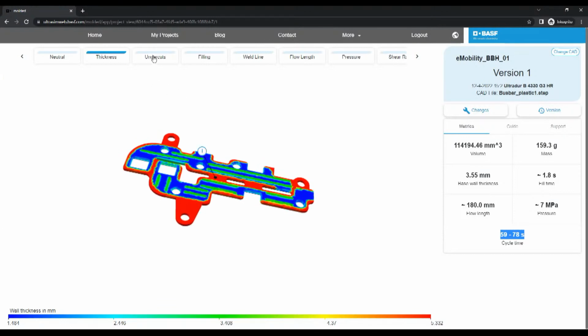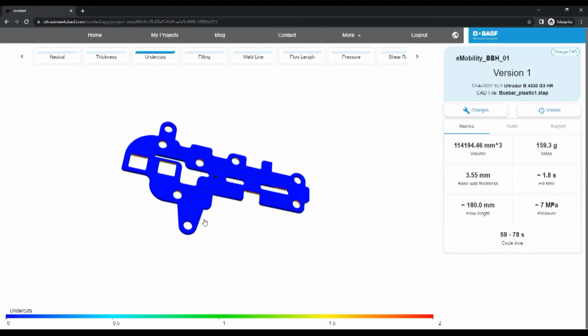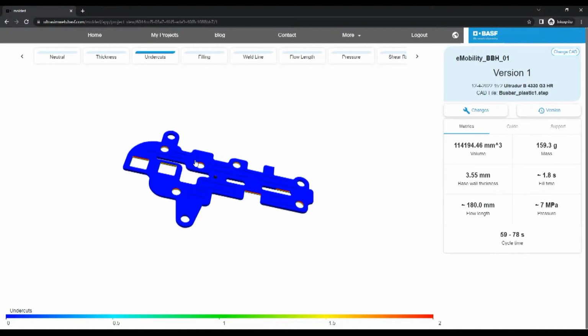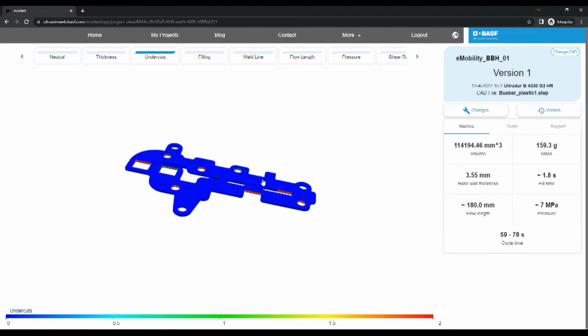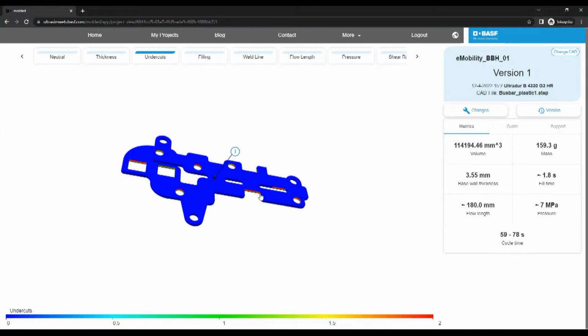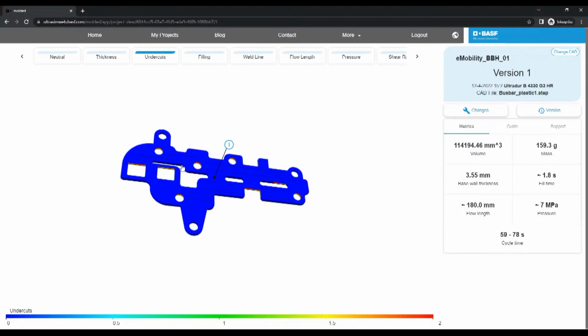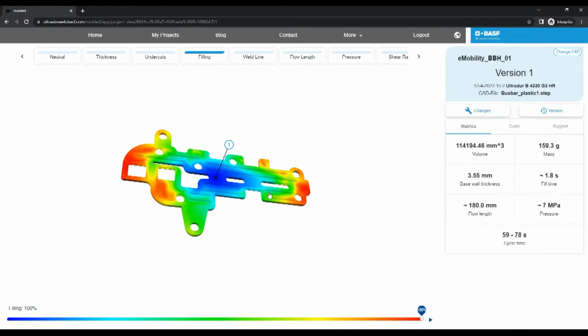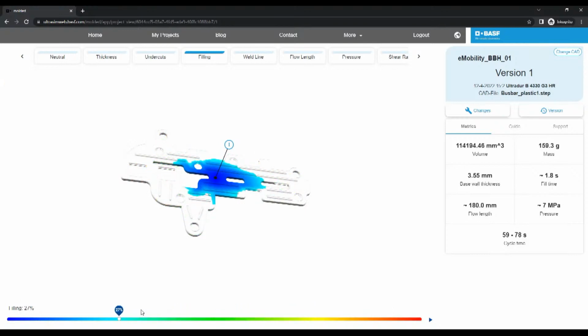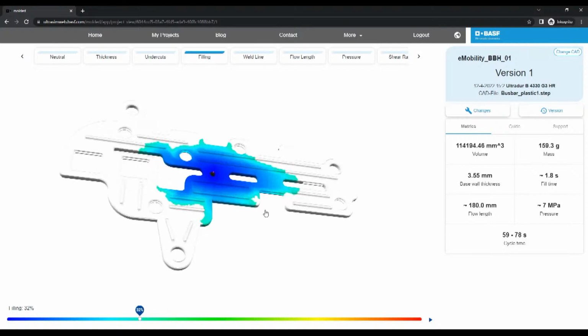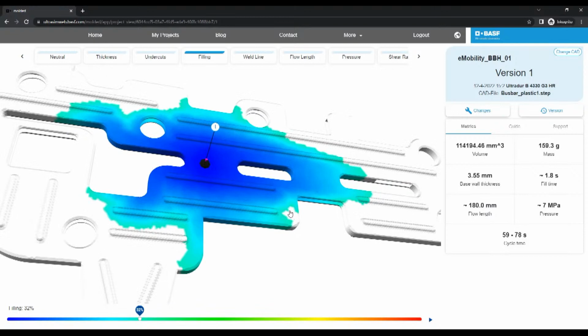With that having said, let's check out the undercuts. This visualization basically shows you whether the part can be demolded from the mold. And here we see some red areas, but due to that as a bus bar holder, the red areas should not pose any problems because this is where later actually the bus bars are. Let's switch to the filling analysis. Here we can check out the flow behavior through the part. I can just simply grab the slider and for instance here I can observe that there most likely is a weld line forming in this area.